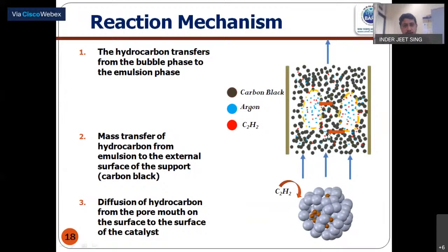I am showing an arrow, and then there will be a mass transfer from the emulsion phase to the external surface of the carbon black. So if this is a carbon black where these are the primary particles, and these are the iron nanoparticles sitting inside the pore. So acetylene, first step is from the bubble phase to the emulsion phase. Next step, from the emulsion phase it is coming to the external surface of the carbon black, which is the external mass transfer.